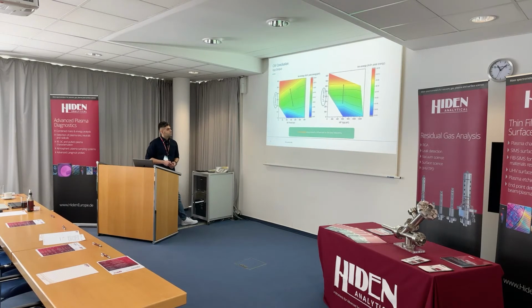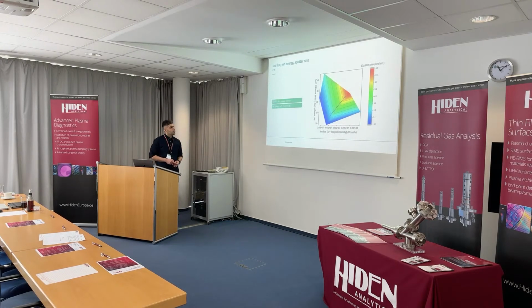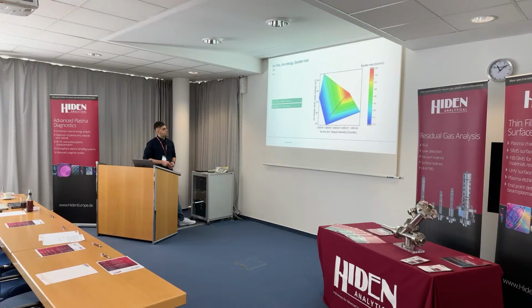And the lower frequency causes higher ion energies. So when the LF power is increasing, the ion energy is increasing, and you see this effect better in LF VPP. And here is the ion flux, ion energy, and sputter rate. So you see the sputter rate depends on ion energy and ion flux, both of them together.